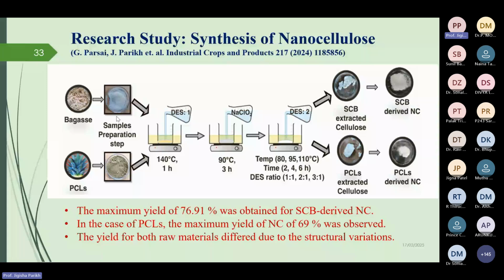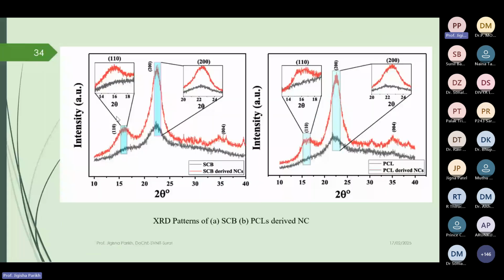So here, instead of the conventional process, we have utilized the DES as a green solvent along with the protonation reaction. Then the product, because we have to validate whether we have received the product as per our requirement, XRD was performed for the derived nanocellulose from SCB and PCL, and this is to identify the crystallinity index with reference to the nanocellulose.